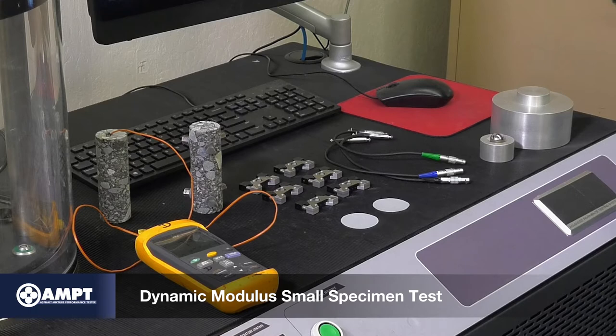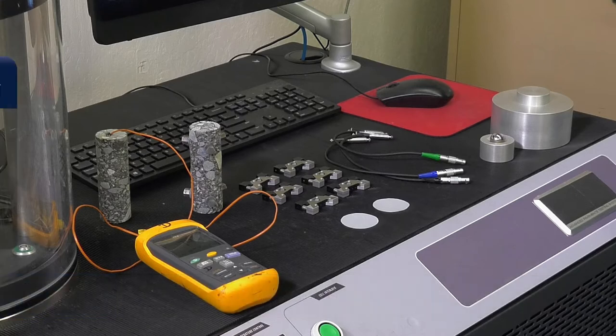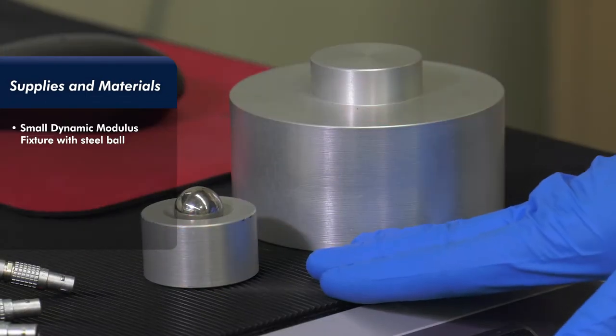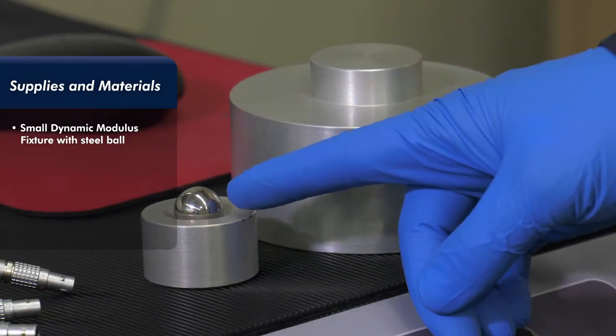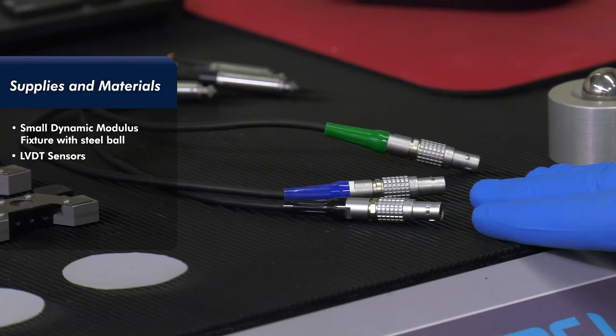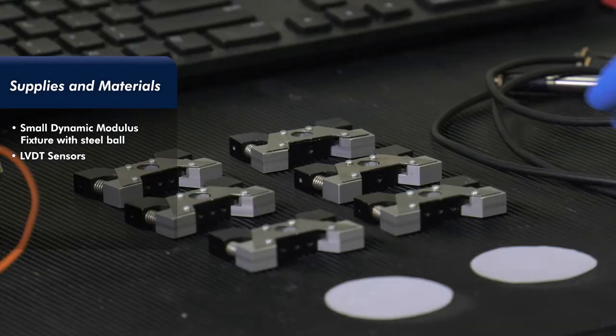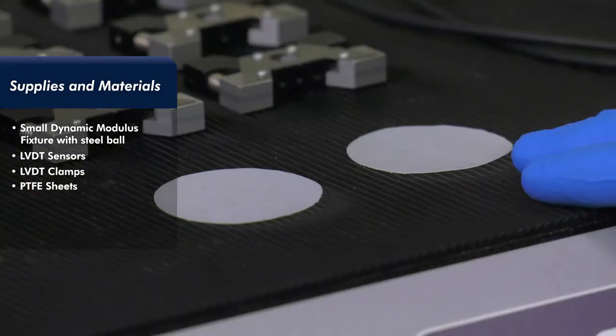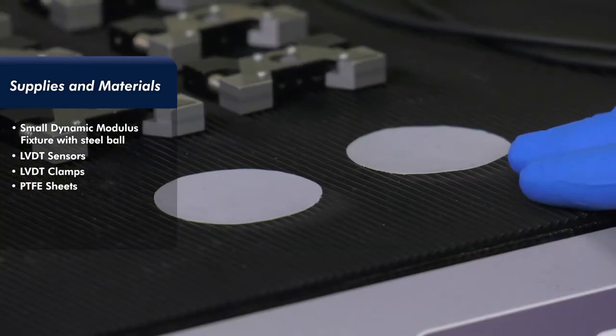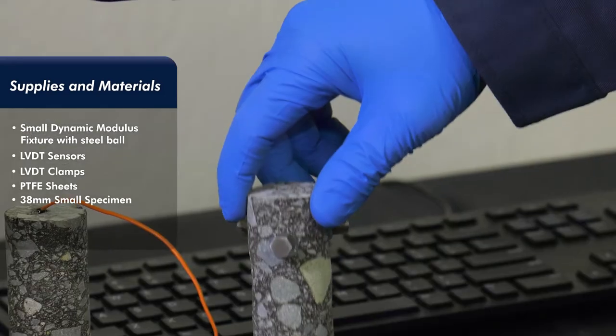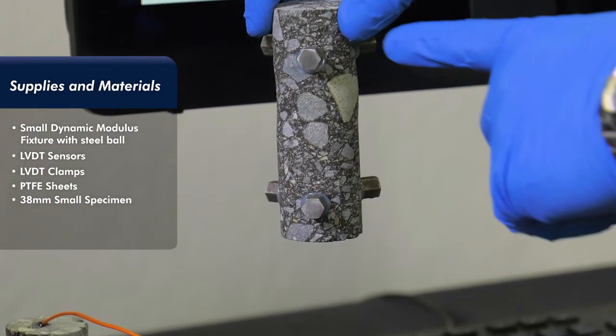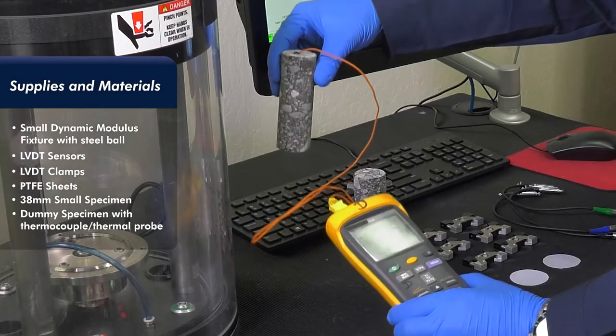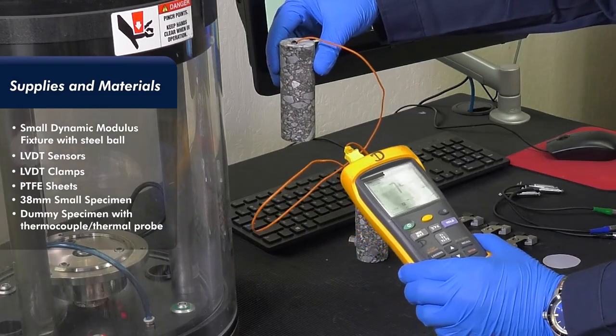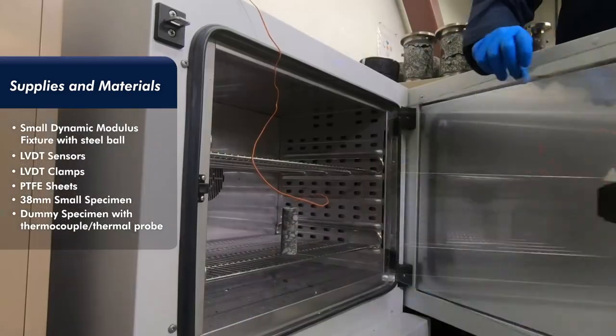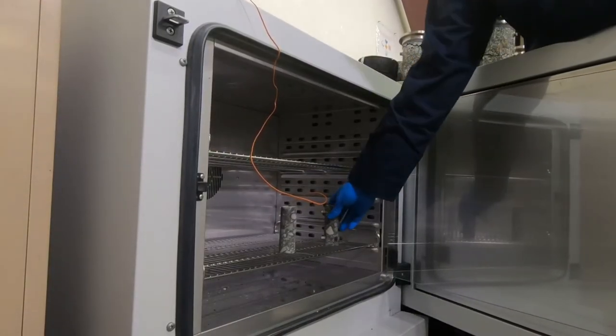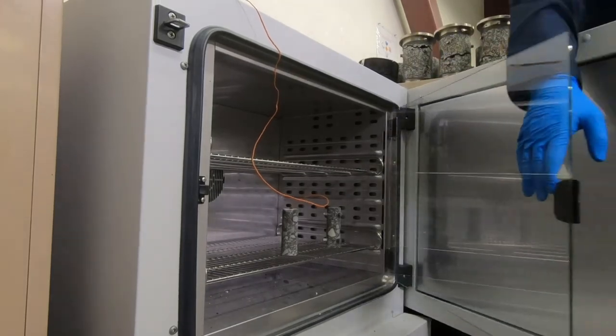Supplies and materials for the dynamic modulus test are shown here and include small-scale dynamic modulus fixture with steel ball, LVDT sensors or specimen-mounted deformation measuring system, LVDT clamps, 0.25mm thick and 40mm diameter PTFE sheet, 38mm diameter by 110mm tall specimen, and a dummy specimen with thermocouple thermal probe installed in the middle of the test specimen. Place both the testing and dummy specimens in the external environmental chamber until the dummy specimen reaches the test temperature.